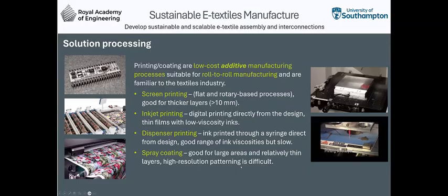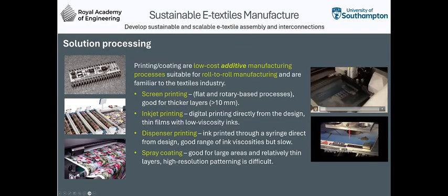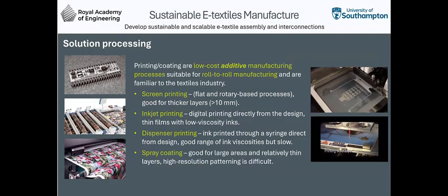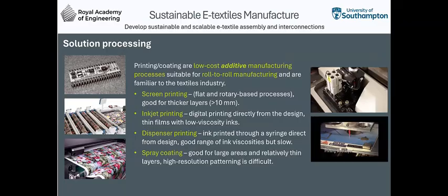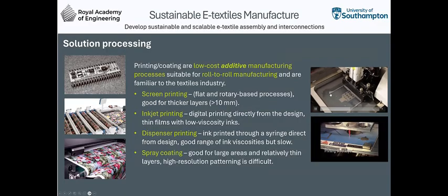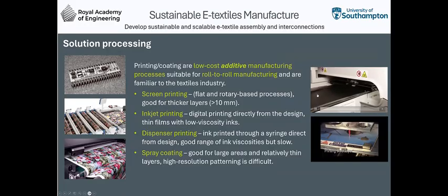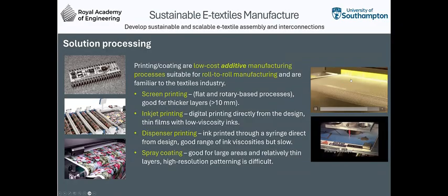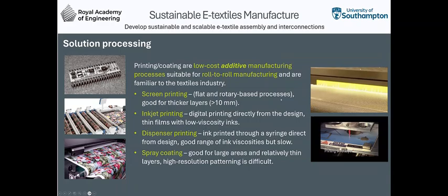The other manufacturing process we've developed for our e-textiles, a way of depositing smart materials onto the surface of the textile, is to use basically standard printing techniques, such as screen printing and inkjet printing. These are widely used in the electronics industry for making hybrid circuits, and also in the textile industry for patterning the textiles. So we have a nice professional electronically controlled screen printer we use, so we can reliably print the functional material. This just shows an example of the functional ink being printed onto the textile. It's simply dried and in this case thermally cured, and we attach our textiles to a rigid substrate just for that printing process.